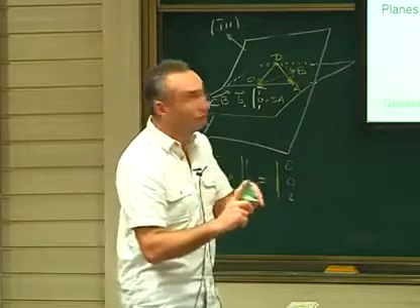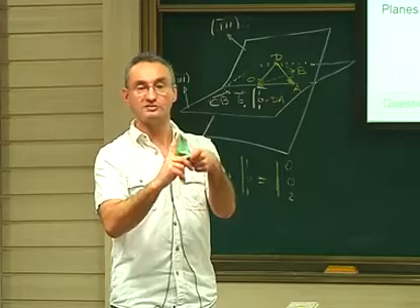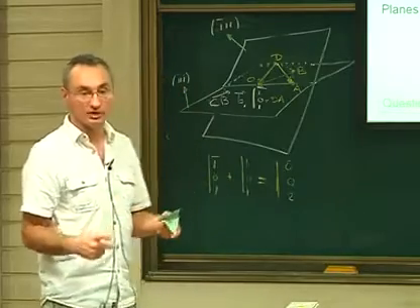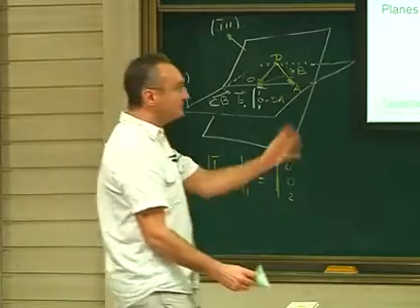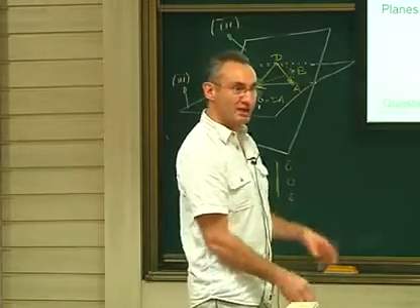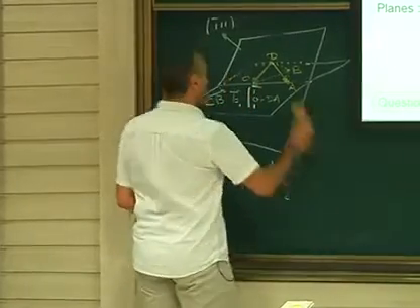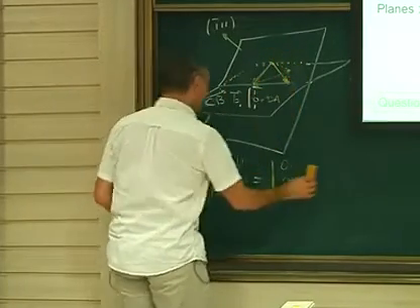We call it the Hirth lock. Okay, the Hirth junction. Hirth junction is this thing when the two Burgers vectors are orthogonal. So it is less strong than the Lomer-Cottrell. I will show you later on why it is less strong. The glissile, and I think we will stop it here because it's quite long and I'm tired. I'm making a lot of mistakes. So I will try to do the last one now. Hopefully I will succeed the first time.